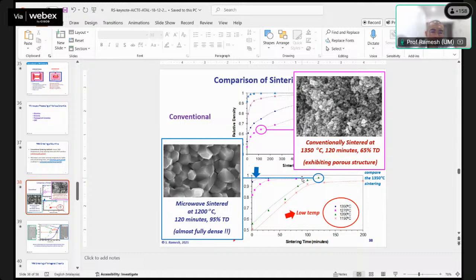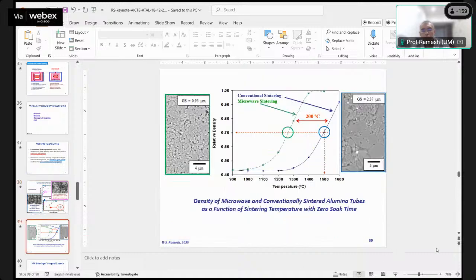But on the same count, we find that when we compare with microwave, keeping the time same, 120 minutes at the same temperature, 1200. All right, now in this case different temperature, this is higher, this is lower. So for the same condition, except for lower temperature, the density is already 95% dense. All right, so we can see that there is advantage of using a microwave to sinter alumina.